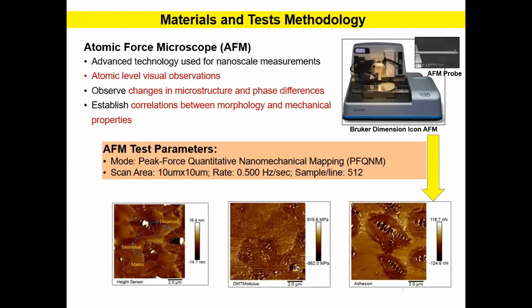In this study, we used an advanced technology for nanoscale measurement. We used atomic force microscope to observe the asphalt binders' micromechanical properties along with its microscopic surface roughness. And we use the PeakForce quantitative nanomechanical mapping mode of AFM, where the scan area was 10 micrometer by 10 micrometer. Here you can see some typical AFM-based maps of height, which is roughness, DMT modulus, and adhesion value.